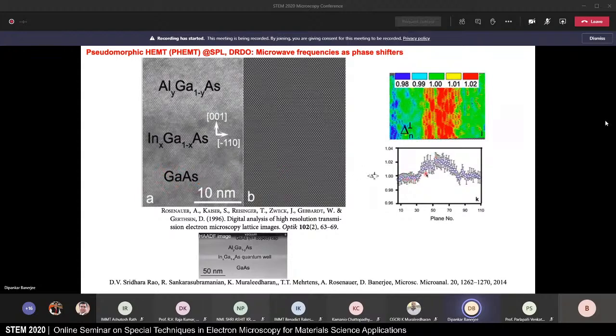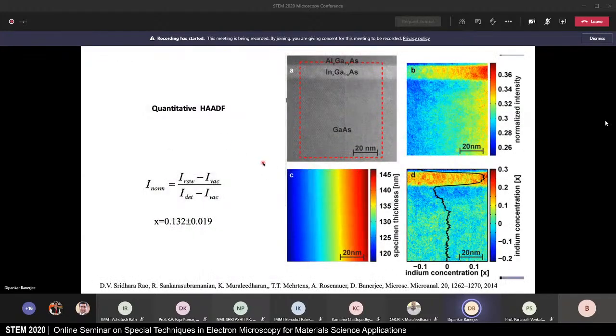And because you can identify the displacement in these layers, you can then arrive at the strain in these layers as a function of the original lattice parameter of the unconstrained indium gallium arsenide. This must be accompanied by a knowledge of composition, because you have to relate composition with the strain. And so Murli and his colleagues, Sridhar Rao and others, achieved this by developing quantitative high-angle annular dark field techniques.